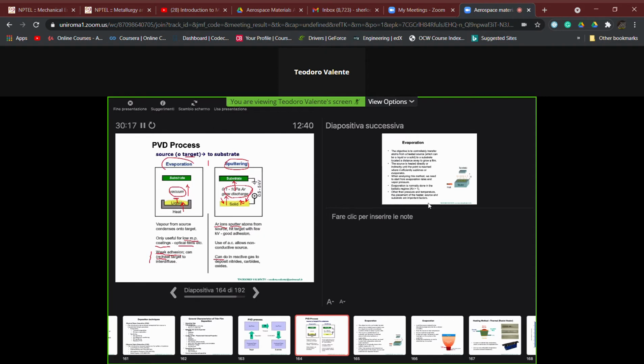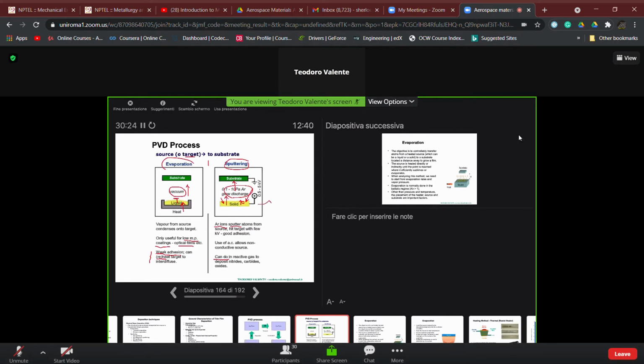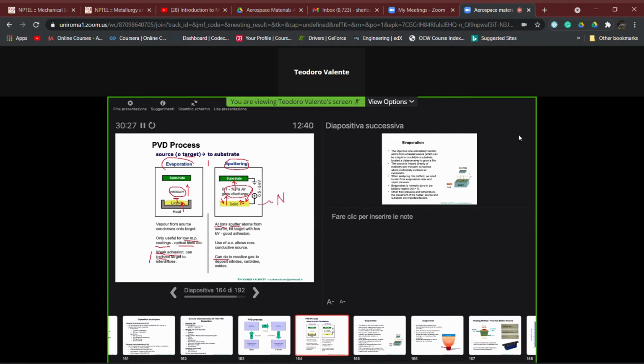You see here, as I was telling you before, if we put a reactive atmosphere inside this chamber, for example nitrogen, and, to give you always the same, most common example, having titanium as a substrate, we can have a reaction inside this chamber between the titanium atoms and nitrogen. We can have the formation, by chemical reaction, of titanium nitride in the vapor phase with a condensation on the surface of the substrate and the fabrication of titanium nitride coatings. This is what is called reactive physical vapor deposition